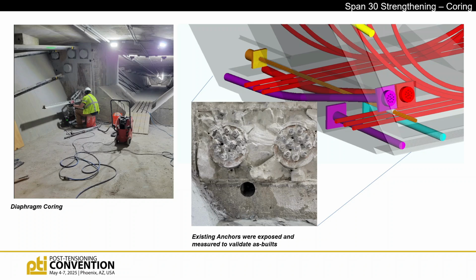As Nick had mentioned, the congestion through those diaphragms is pretty intense, and we also got a really good lesson on the limitations of GPR up front. We think that the GPR technician may have looked at the drapes and was worried about where the tendons were, and I think he drew tendons everywhere. So we almost had to throw the GPR away and realize he was probably picking up the regular steel and very likely imagining that that's where there were draped tendons. And then one of the things we had playing to our advantage was taking the blocks off of those two existing anchors and making sure that they're where they were supposed to be. We measured them based on the center line of the span, and it was within a 1/16 of an inch. I'm not sure that I hit the center line within a 1/16. So I was pretty convinced that the existing tendons and the anchors were where they were supposed to be.